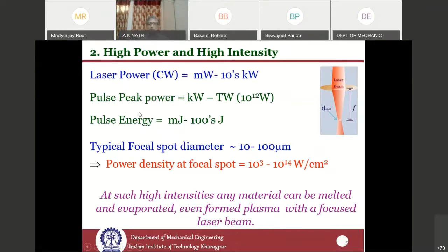When you use pulse lasers, you can get power levels from kilowatt to terawatt, with pulse energy up to hundreds of joules in a single pulse. Once you focus such high power laser with a lens, you can generate a focal spot diameter practically in the range of 10 to 100 micron minimum spot size, yielding power density at the focal spot in the range of 10 to the power 3 watt per centimeter square to 10 to the power 14 watt per centimeter square.